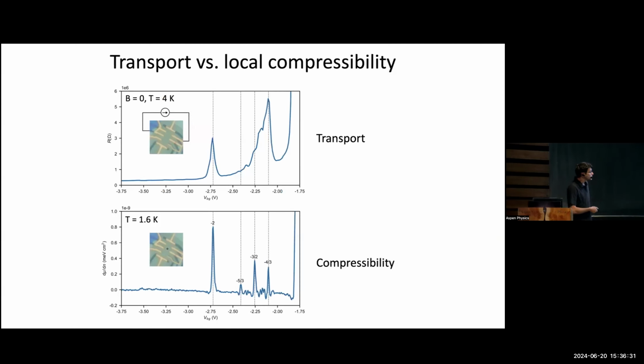I want to just flash this quickly, comparing what you see in transport across the device to what we see when we measure local compressibility with the single electron transistor in a particular spot highlighted here in black. You can see there are some peaks that we observe in transport. If you were just to see these peaks, you have no idea what's going on. Look in compressibility locally, all of a sudden everything is much, much clearer. So I've labeled these with some numbers. I'll describe why in a second. But you can see there's a dramatic difference in the quality of data, or how much you can resolve from a particular measurement.